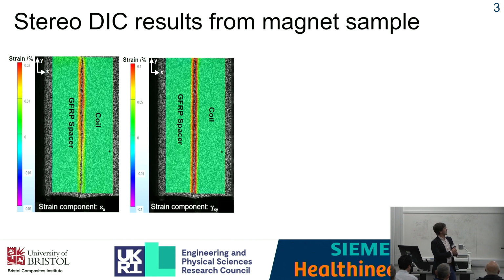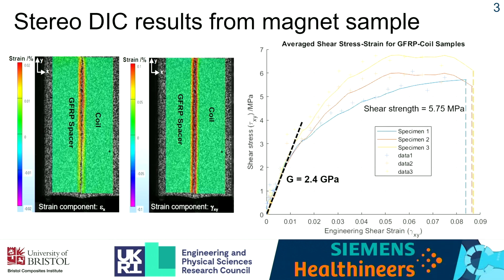So from the results, here we have the strain components in the transverse and shear directions, and the transverse strain component has a maximum amplitude of about 1/5 of the shear, and this shear distribution is very uniform across the interface. So when we plot the average shear stress in the cross-section of the adhesive bond against the observed shear strain, we find a shear modulus about 2.4 gigapascals and 5.75 megapascals for the shear strength.